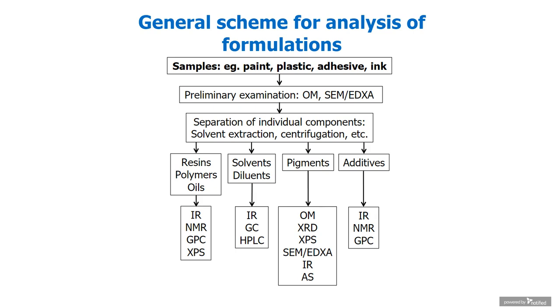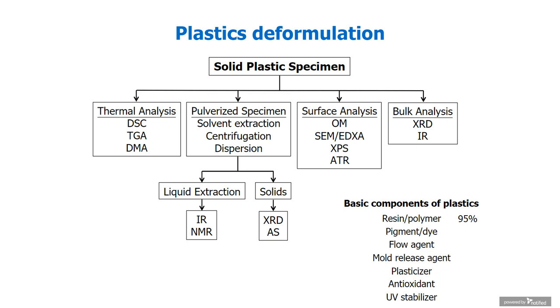So just by looking at this chart, you know it's a lot of work. And the separation is not a guarantee that one can isolate pure components and even assign specific composition or purity. Now, in plastic deformulation, this is very specific. One can deal with a solid sample. Usually, thermal analysis is one of the easiest ones to use in terms of DSC, TGA, and DMA that allows us to look at the degradation temperature, the presence of a melting point or a glass transition temperature.